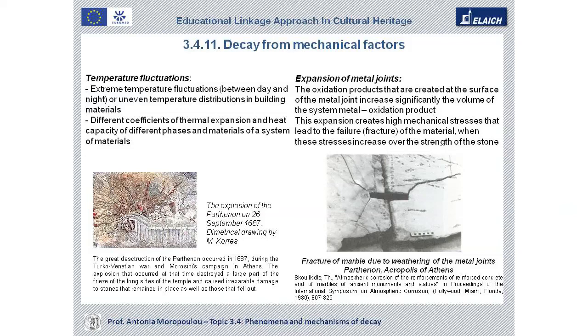Here we have another dramatic phenomenon, a fracture of marble due to weathering of the metal joints inserted by the Balanos restoration in 1912 in the Acropolis of Athens. Professor Skoulikidis studied where the metal joints were inserted, and substituted iron metal joints by titanium.